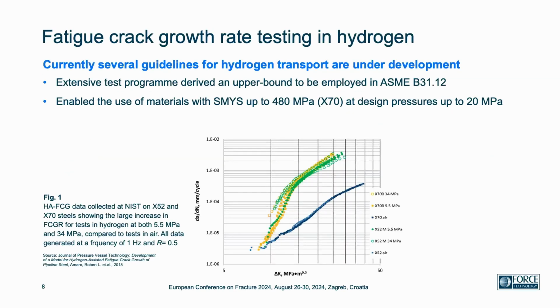Next, we have the fatigue crack growth rate testing in hydrogen. Extensive test programs have shown that hydrogen has a significant effect on the fatigue crack growth rate compared to in-air testing. The curves shown here are from a NIST project where X52 and X70 steels show the large increase in fatigue crack growth rates at both 55 bars and 340 bars compared to tests in air.